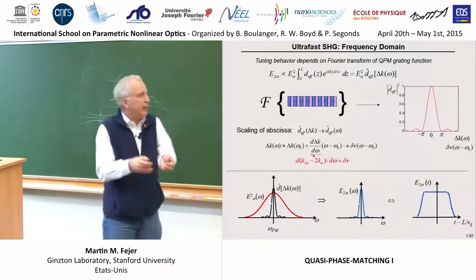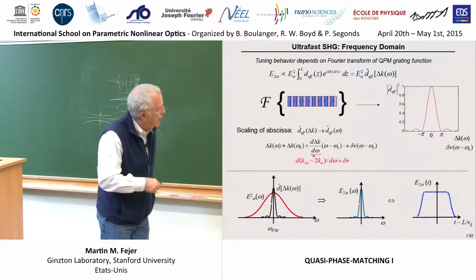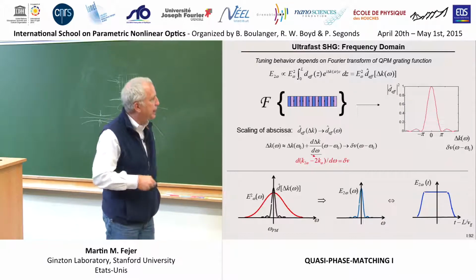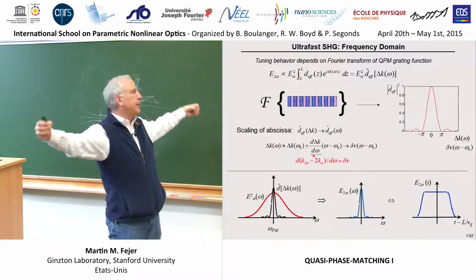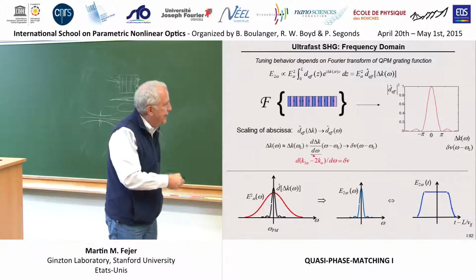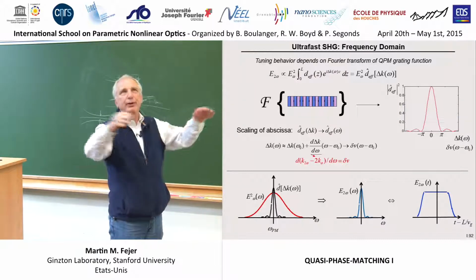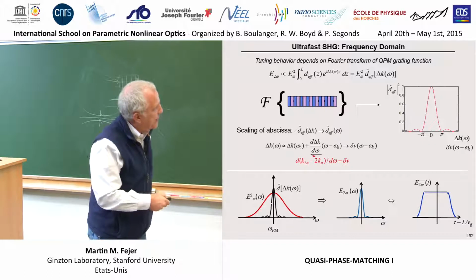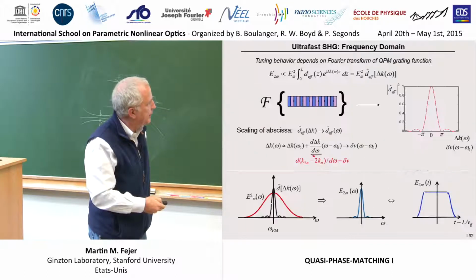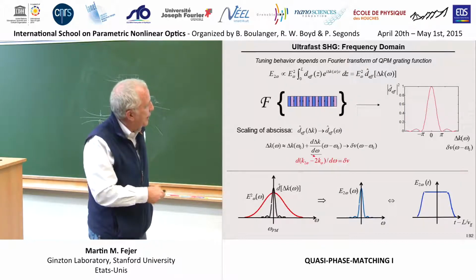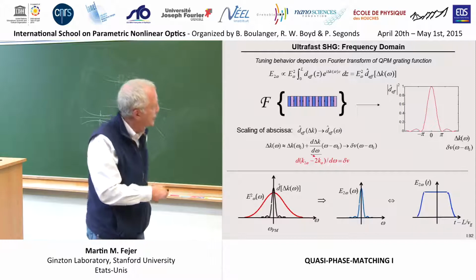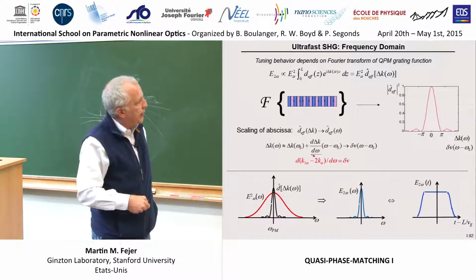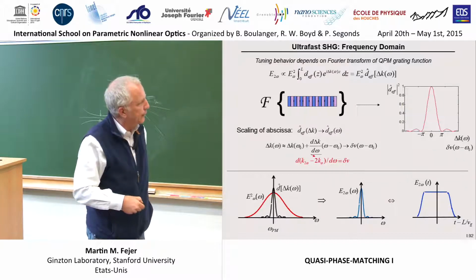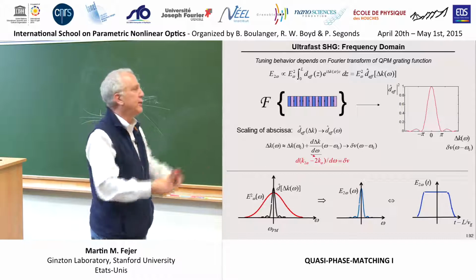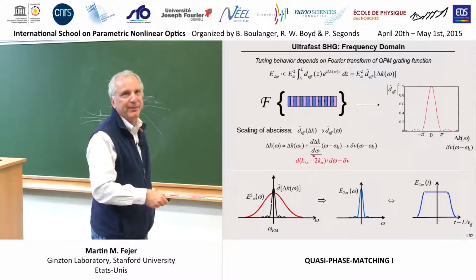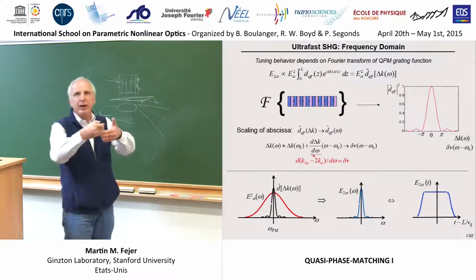And so you can view this as a filtering process. You have this spectrum of the square of your pump. You have this response of your nonlinear medium. So to the extent that the nonlinear medium is long enough that this sinc is narrow compared to the spectral bandwidth of your pump, then what you get out at the second harmonic is basically just the sinc. It's just filtered out something from the peak of this spectrum. And if this is what the spectrum of our second harmonic looks like in the frequency domain, in the time domain, it's just the Fourier transform of this sinc, which is a top hat. And that's exactly the top hat we just found from our time domain arguments from the walk-off.